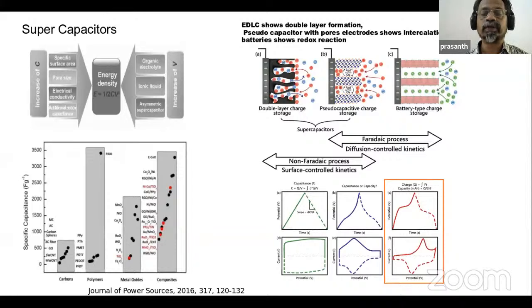By making it into a tubular structure, you can improve the electric double layer formation inside the structure. So an electric double layer capacitor is a good possibility with this nanotubular structure. That comes from the porous nature of the material. When you are making small and smaller pores inside the surface, more surface area can be generated. That will give a high electric double layer formation inside the porous structure of the capacitor.